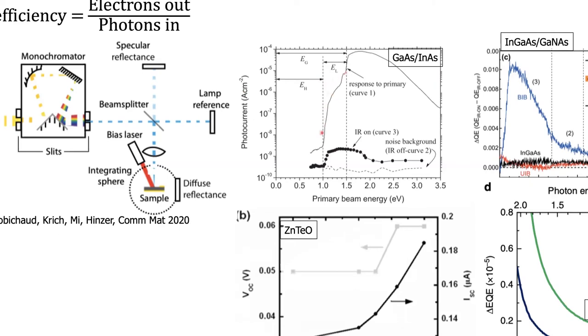This is the response to the primary beam. This is the change that they get when they add the infrared. And you can see they measure it. It's there. There's 2-photon photocurrent, but it's 4 orders of magnitude smaller than what they get from the primary beam itself.